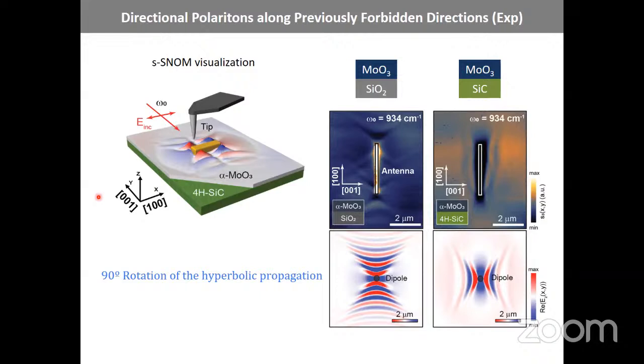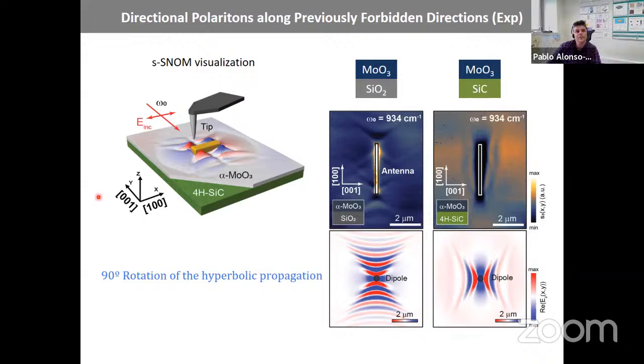Normally this is phonon-phonon scattering, because of anharmonicity effects. In principle there is two-phonon scattering, three-phonon scattering. Defects are also there, but normally these materials are kind of pure. They don't have many defects. Actually, we can do it even isotopically enriched. It's not the main mechanism of the loss, but rather the phonons that are coupled to the light also couple between them, and then they scatter between them, and you lose part of the energy because of this.